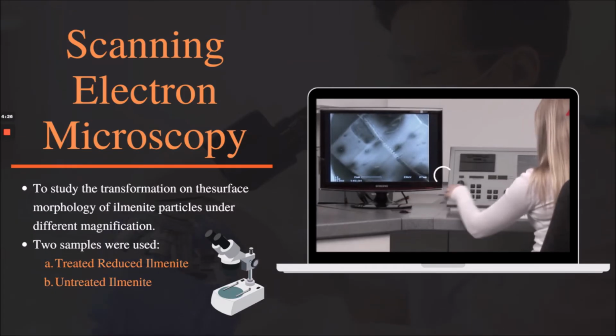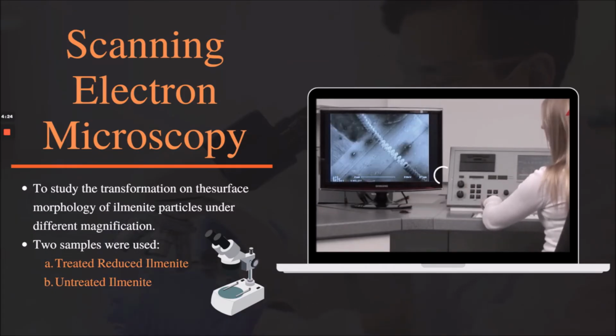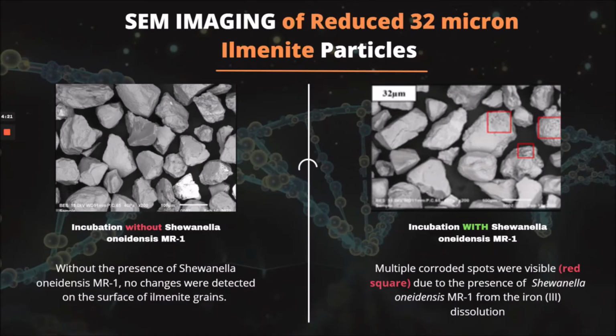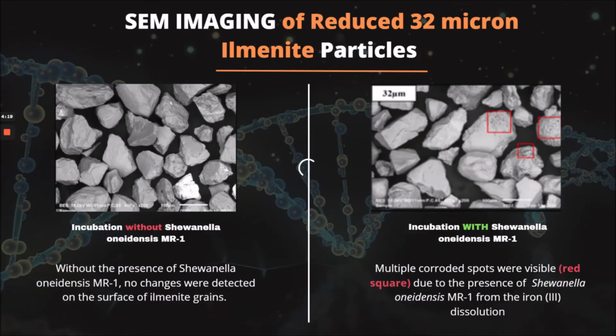The results we obtained from the scanning electron microscopy were much more interesting because, as you can see in the images here, there are noticeable changes in the morphology of ilmenite grains, with and without Shewanella. I'd like to emphasize that the picture on the right, treated with Shewanella, has several spots that seemed corroded, which were absent in the left picture, the negative control without Shewanella. To sum up, we suggest that Shewanella indeed leached these iron oxides from the grains, causing the corroded spots, as you can see on the screen right now.